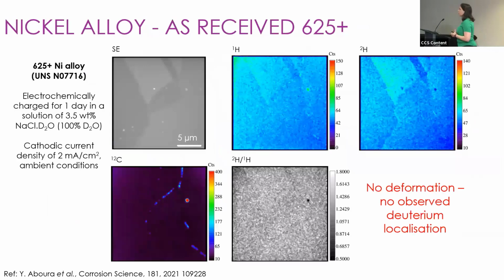The other work that Yasa did was to look at a nickel alloy, which was 625 plus. This is a project in collaboration with BP ICAM, so it's interesting for the oil and gas industry to look at this particular alloy. The first thing we did was to look at this nickel alloy in the as-received condition. You can see it's got a very clean microstructure as shown by the secondary electron image. And if you look at our ratio image, you can see that we don't actually see any localized deuterium whatsoever in this sample. And that's because we have no deformation.